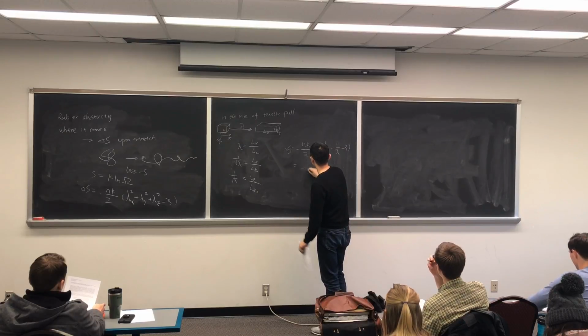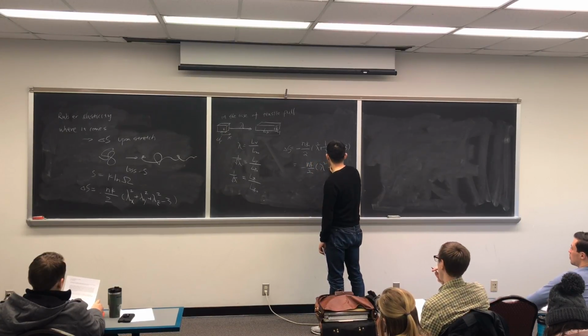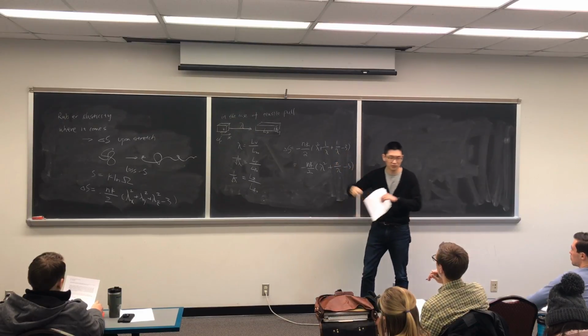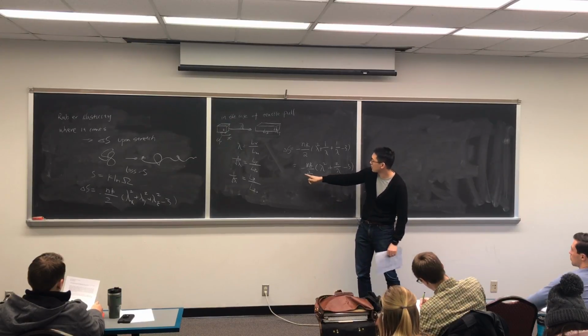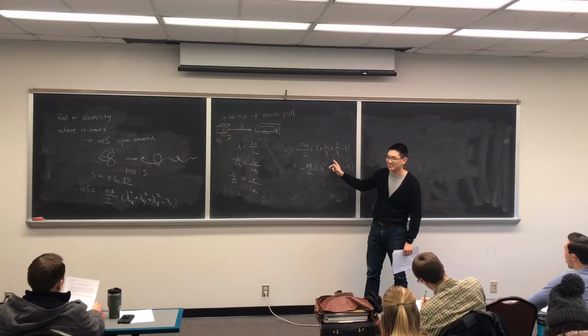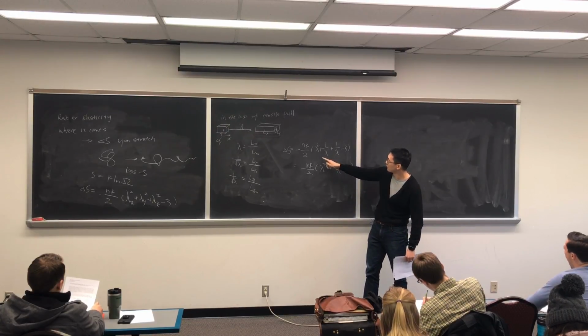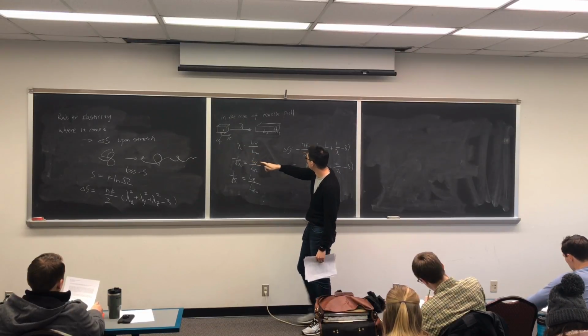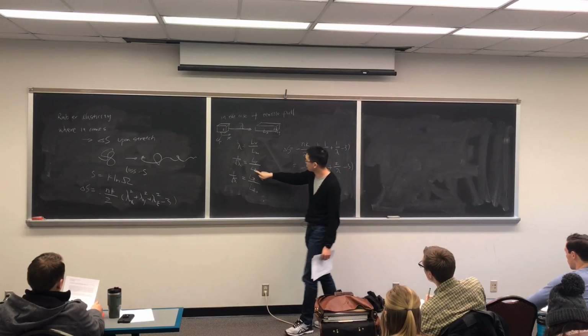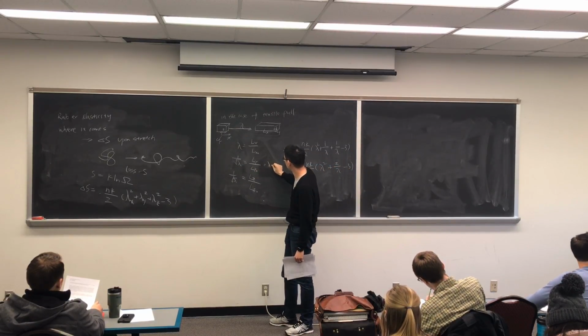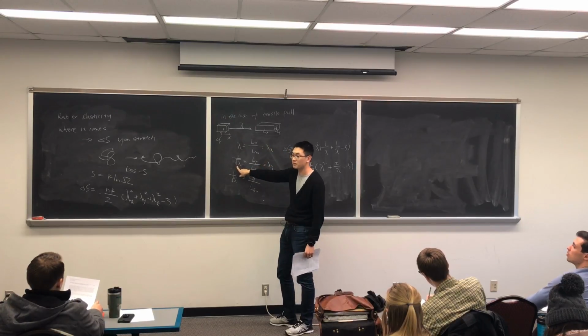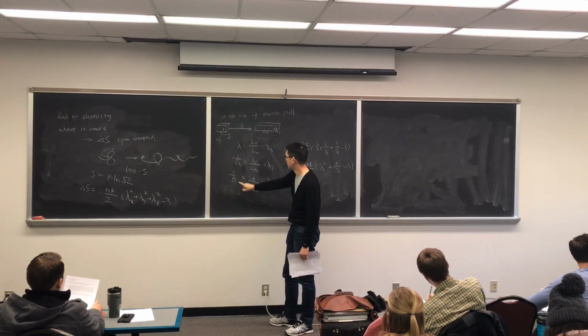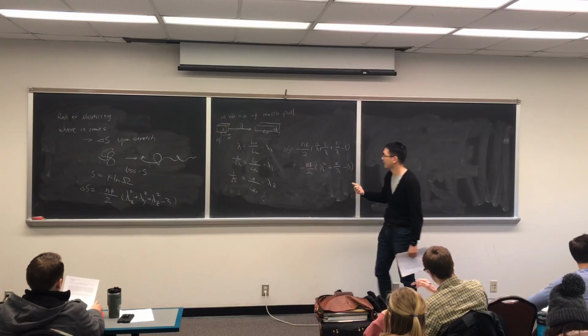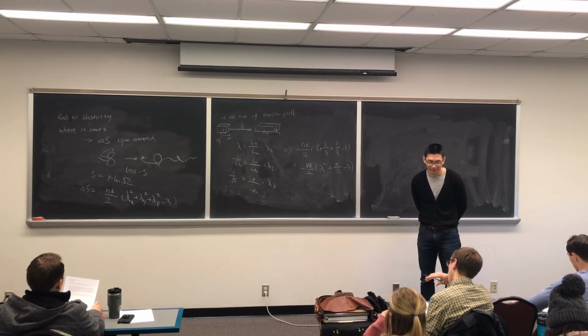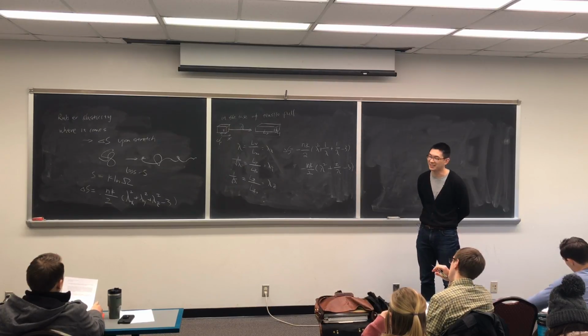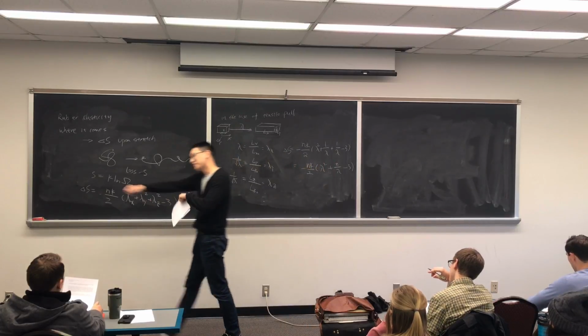So this would be a case where you have a film and you just draw it unidirectionally. That's the entropy you would lose in the x, y, z directions. Right? Lambda x is basically equal to lambda. Lambda y would be, this is lambda y equals 1 divided by root lambda, and the lambda z direction will be the same. So that's how much entropy you lost in the special case where you just pull the film in one direction but not two directions.